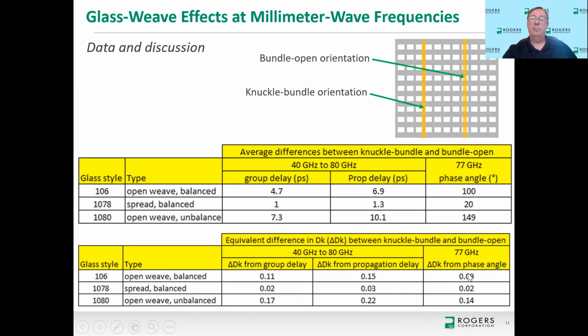Now the table of information below that is just the exact same information as above, except what we did was use the information on the top table to extract the dielectric constant of the material. So what we found was the 106 glass, we saw a dielectric constant difference due to how these circuits behaved with the knuckle bundle orientation compared to the bundle open orientation. We saw a Dk difference of 0.09 with the 106 glass, with the spread glass 0.02, and then with the open weave unbalanced 1080 glass 0.14.